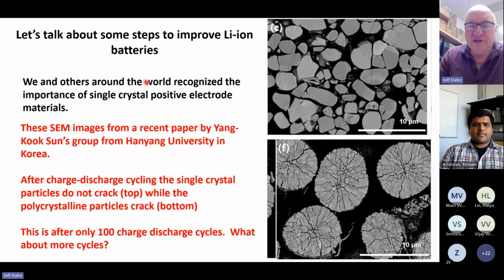So how can we improve the situation? Well, we and others around the world recognize the importance of what are called single crystal positive electrode materials. So these are SEM images. The lower one is for typical NMC after 100 cycles, and you see this microcracking. And these are single crystal materials where every particle of the positive electrode is one crystallite. There are no grain boundaries. And after 100 cycles, there's no microcracking observed at all. So here you won't lose electrical contact to the particles in the middle and have capacity loss.